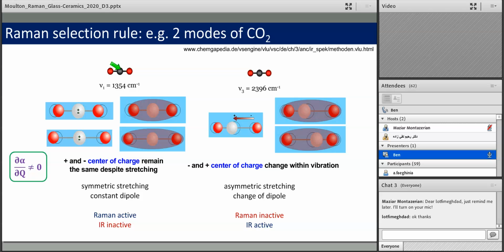In the case of the symmetric stretch on the left here, if we drew an ellipse of the electron density, and we relate this to how well it interacts with the incoming photons, you can imagine an ellipse here that's larger when the bonds are stretched, right here, and smaller when they're compressed. And so this change in the size of this ellipse, we call the polarizability ellipse, is what allows for a non-zero solution in our coefficient here. This means that as a result, this vibration here is what we call Raman active, so we will see a peak in our spectra that we can assign to this vibration.